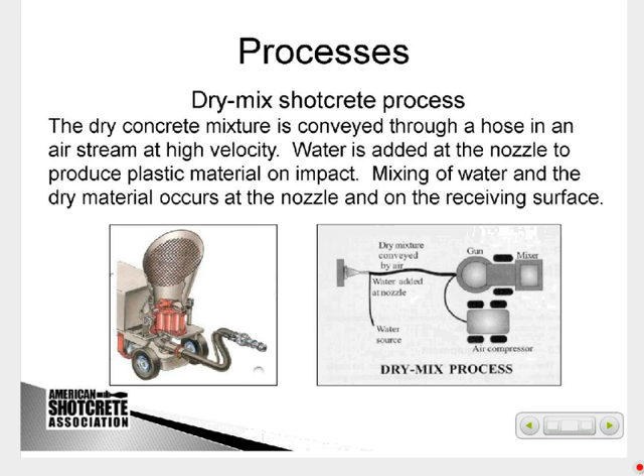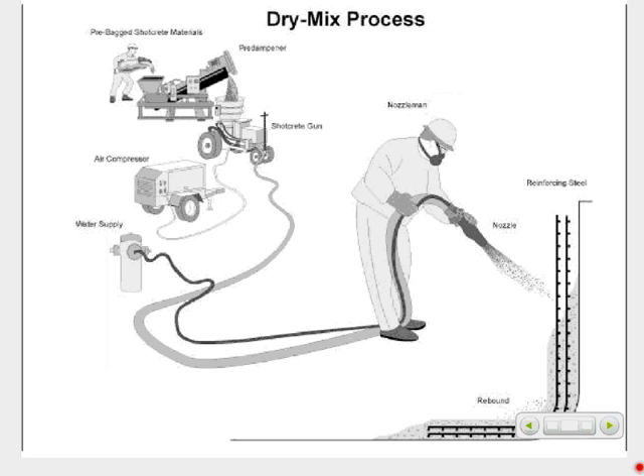There's two basic processes, dry mix and wet mix. Dry mix, you can see the photo or the picture in the left-hand side. That's a small rotary gun. These were introduced in the 50s versus that dual chamber gun like Akeley introduced in the early 1900s. But in a dry mix process, we basically take the material, put it into a gun. The gun then takes air pressure and pushes that material through the hose. At the end, the nozzle is attached to a water line. Water is physically injected into the stream. That's where we hydrate the material and then shoot it in place.